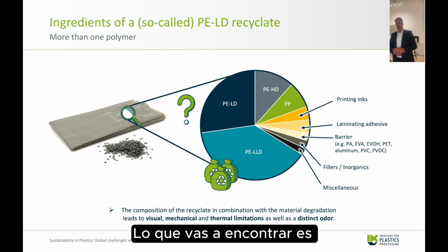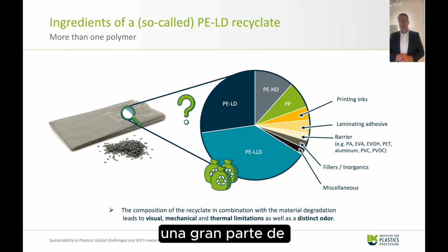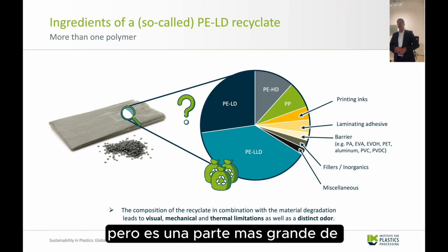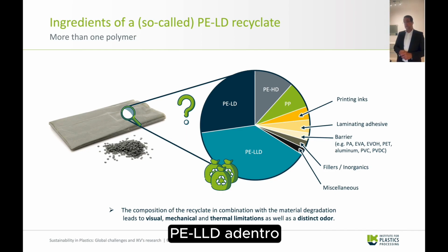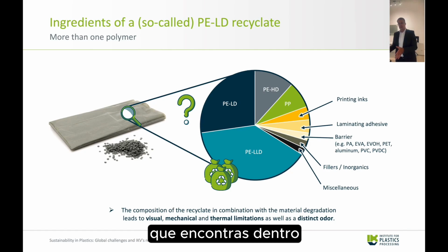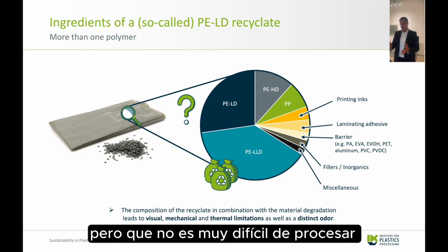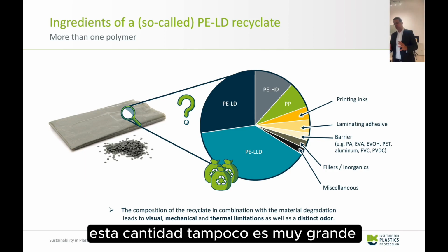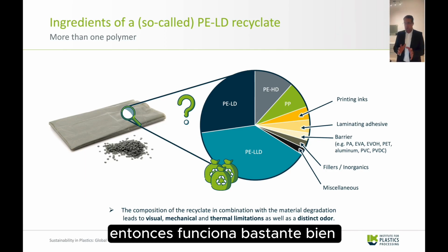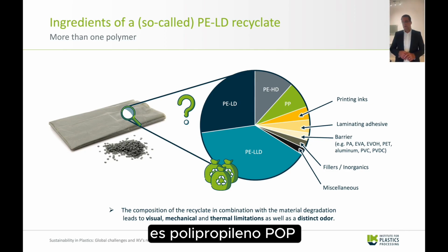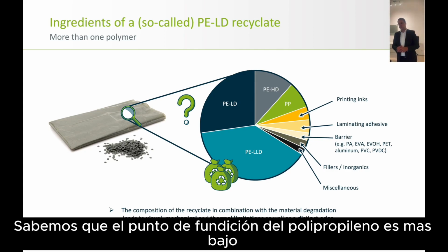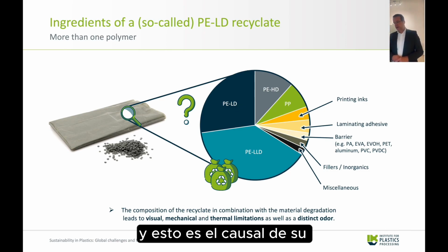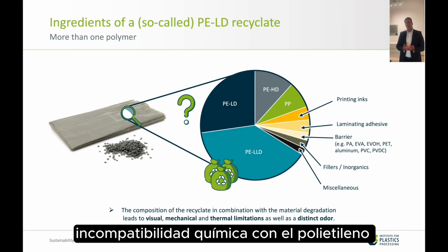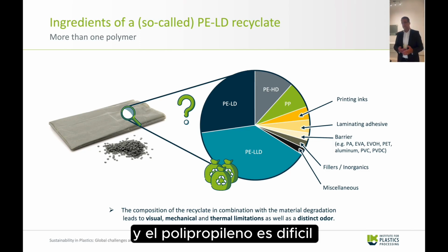What you find is there is a major share of PELD inside, but there's an even bigger share of PELLD inside. And there is a share of PEHD inside. So the full collection of polyethylene you will find inside, which is not really nice, but not too hard to process because the melting points are similar, viscosity not too far away. That works pretty well. But then we also find some polypropylene. And for polypropylene, we know that the melting point is much higher, the viscosity is different, the chemical compatibility between polyethylene and polypropylene is difficult, and so on.